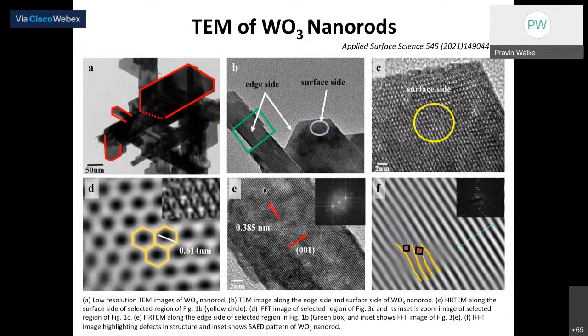So this is a TEM image of WO3 nanorods. Okay, so you see here, these nanorods are randomly overlapped on each other, so it's very difficult for our beam to pass through and get proper shadow images. But if you focus on another part of the region, you can clearly see here these are the edges, facets, right, on this edge. So these facets in the shadow images can also be seen properly. So this is the edge side, and here is the surface side.